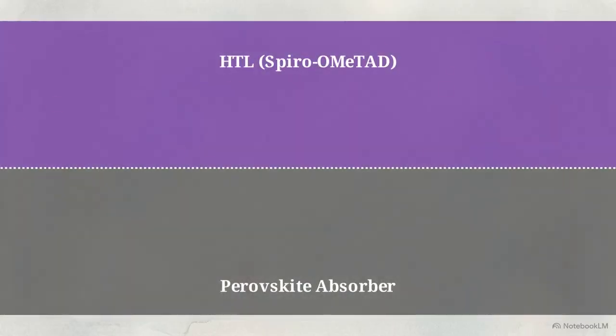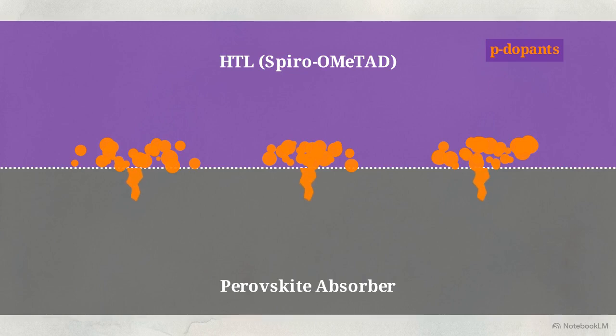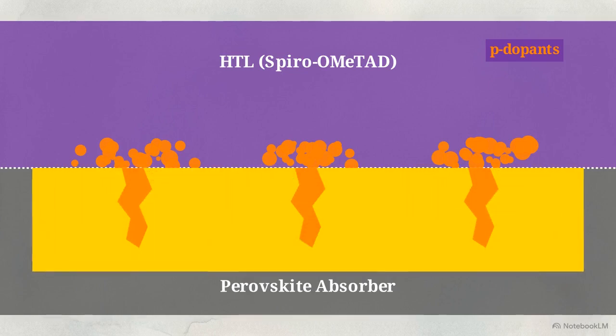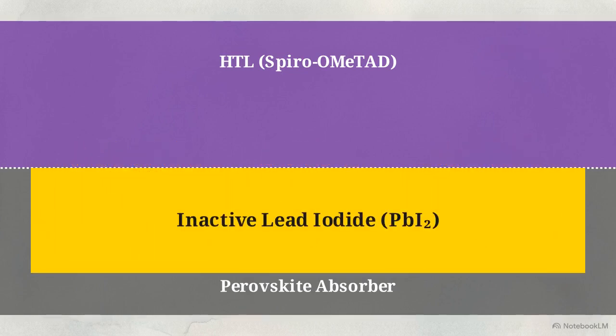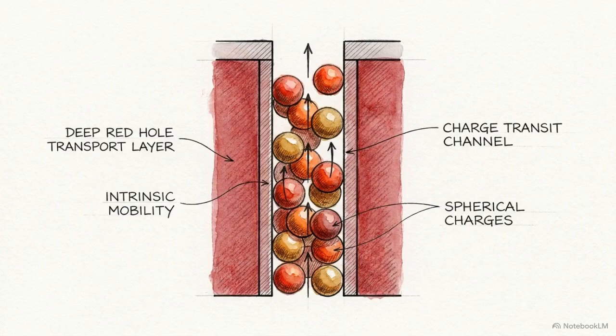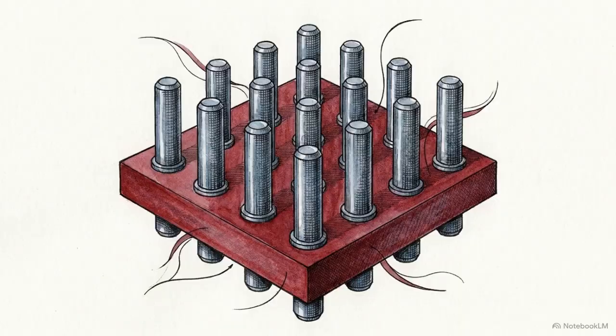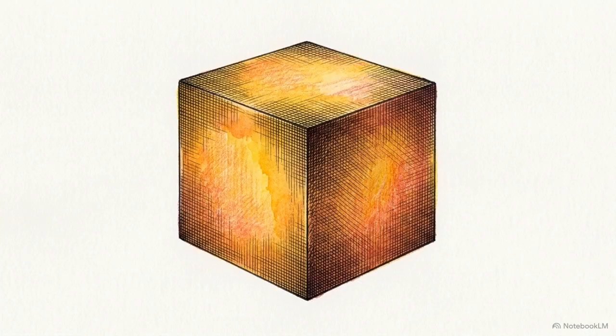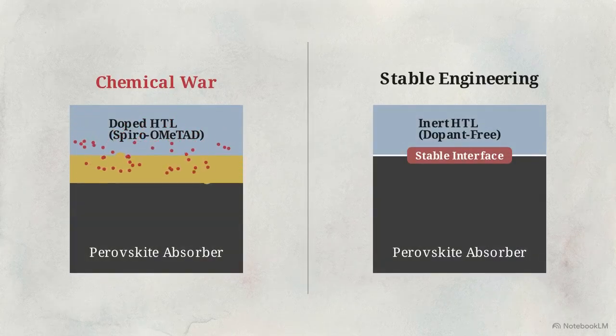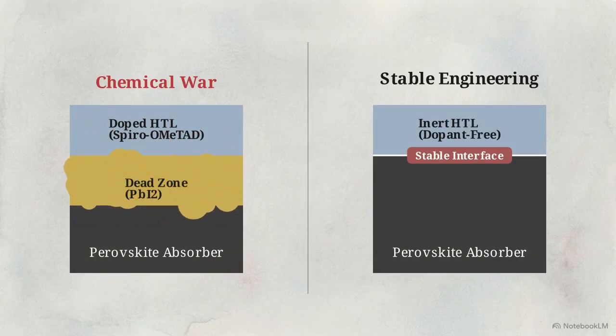The aggressive oxidation process bleeds directly through the boundary, decomposing the active perovskite into inactive lead iodide. The modern solution is to engineer entirely new, dopant-free transport materials, utilizing fluorinated organics or inorganic copper thiocyanate (CuSCN) films. With intrinsic hole mobility, they extract charge rapidly, without hostile chemical environments, extending the cell's lifespan. Achieving long-term stability requires abandoning reactive dopants in favor of chemically inert transport layers that do not wage an internal chemical war against the core absorber.